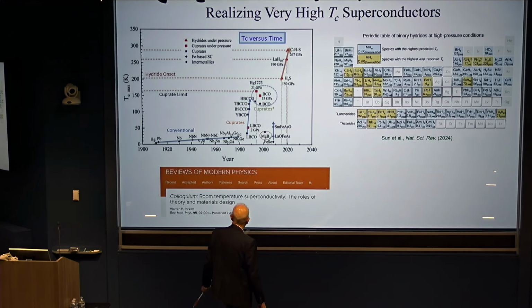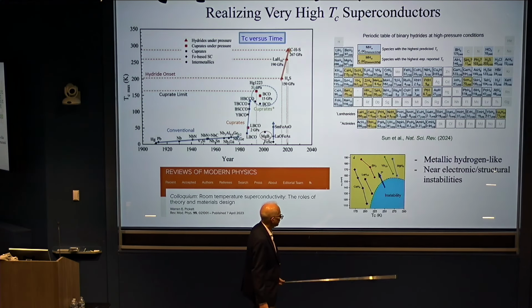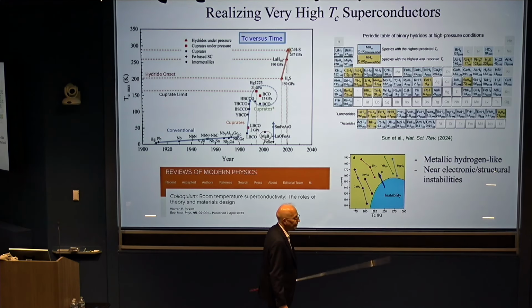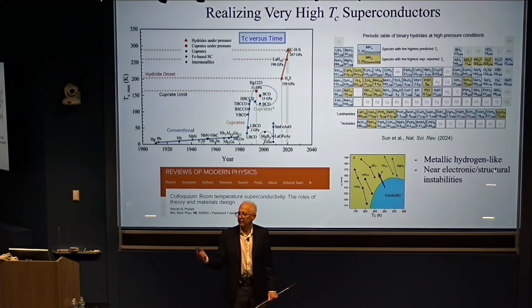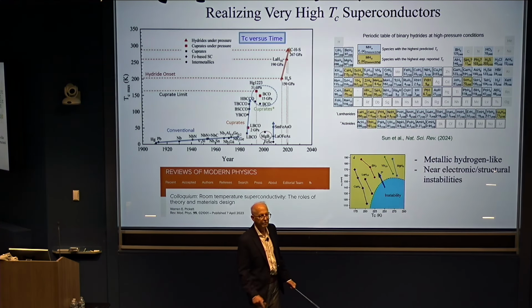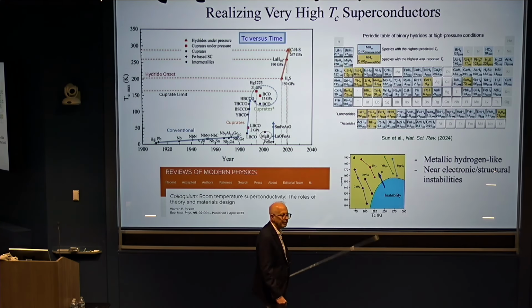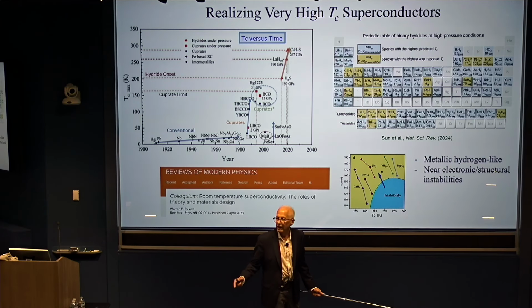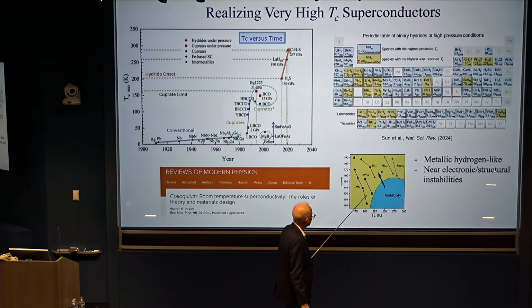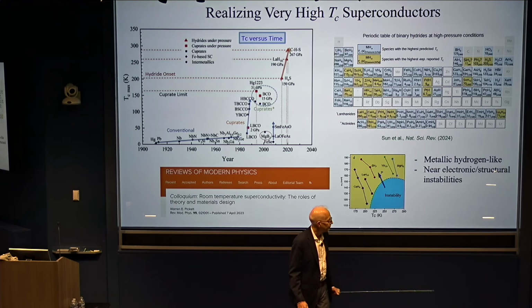This is summarized in a beautiful paper by Warren Pickett. And he also made an important point that I'll come back to at the end, and that is in all of these cases, and this goes back to some of the earlier ideas about superconductivity, the maximum TC in the superconductivity is always close to some kind of structural and electronic instability, which is a challenge actually for theory. And there are also, in these calculations, really metallic hydrogen-like materials. It's kind of like doped metallic hydrogen.